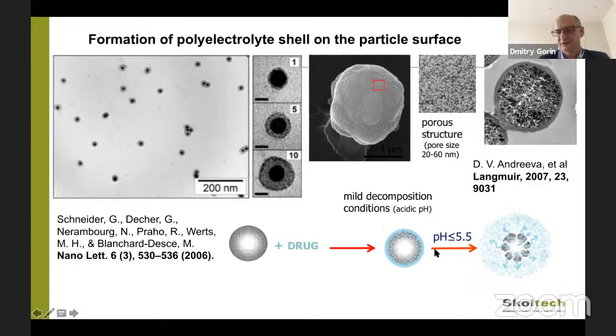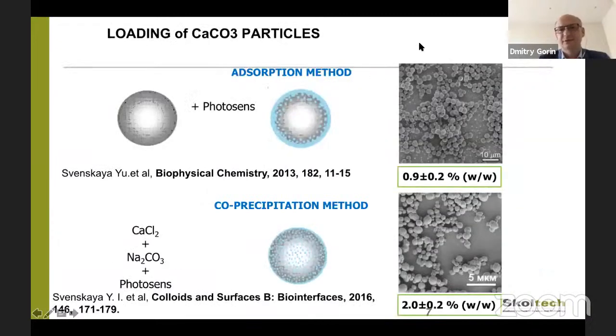Because, for example, if we take into account calcite particles, they can dissolve at pH 1. And we used, as usual, two types of methods for loading these substances, such as drugs. Two technologies, the adsorption method and the co-precipitation method. And in this case, we obtained low loading efficiency, like 1% and 2% by mass. And of course, we are going to increase the loading efficiency.